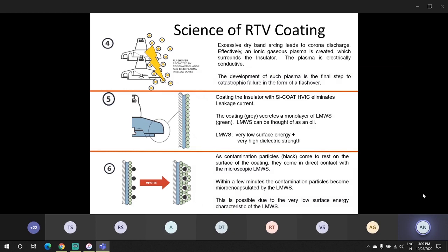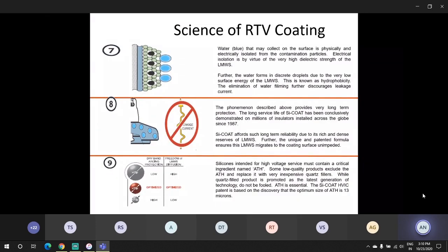So when there are contamination deposits on the insulator surface, the low molecular weight silicone encapsulates the contaminant and prevents it from coming in contact with the moisture. The science is the same as the polymer insulator. So the key to this technology is water is prevented from coming into contact with the pollutant, and the insulator surface is kept dry, and because the insulator surface is kept dry, there is no electrical discharge activity on the surface of the insulator.